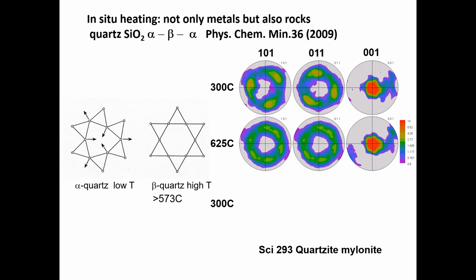We can not only apply to metals, but also to rocks. Now, quartz goes through a phase transformation from low quartz, which is trigonal, to high quartz, which is hexagonal at about 570 degrees. So first you have this, now a quartzite, polycrystalline quartz rock, which is strongly textured. C-axes are here, and then these rhombs indicate the trigonal symmetry. As you go to 620, it switches, it becomes hexagonal, and so there is no longer this trigonal symmetry.